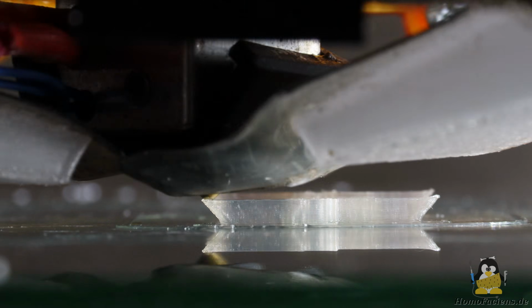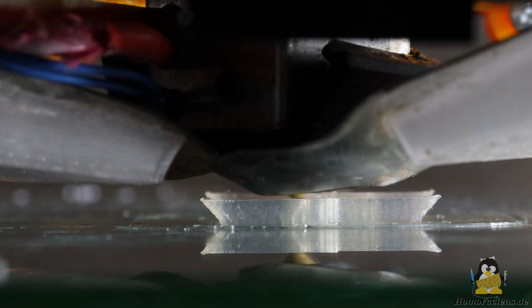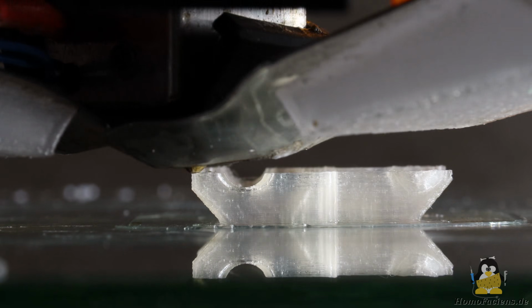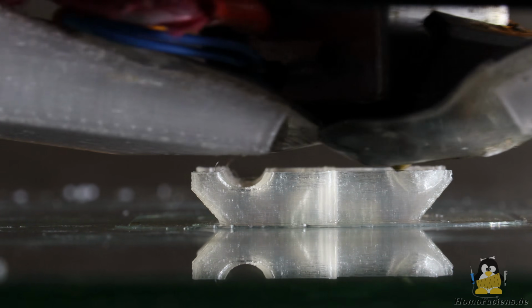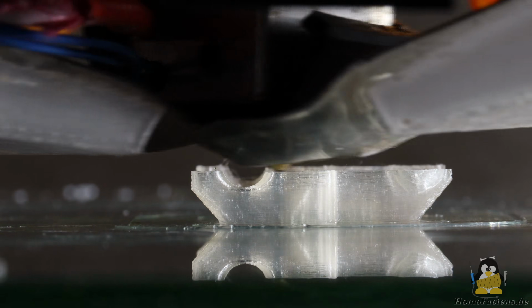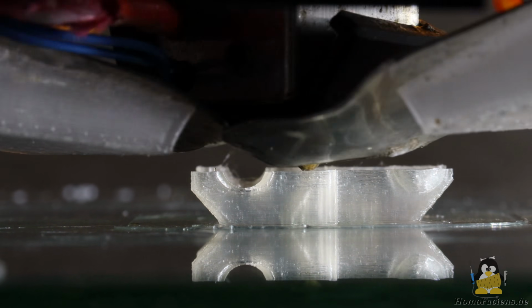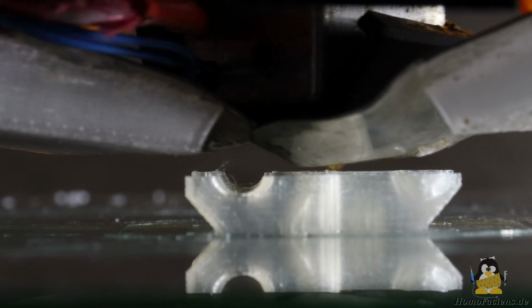Encouraged by this excellent print result, I halved the layer height to 0.1mm for the next test, keeping all other parameters identical. The extruder now has to precisely dispense even smaller volumes of molten plastic. This works very well too. In a later video I will take a closer look, quite literally, at the challenges involved in printing very small structures. Before I can do that I need to upgrade both the Prusa printer and my camera equipment. I will also upgrade my powder mills to obtain better raw material for the prints. After all, I demonstrated in this video that finer is better.